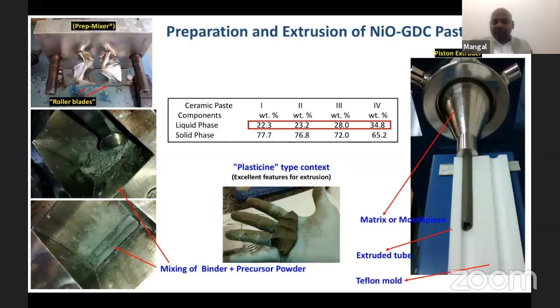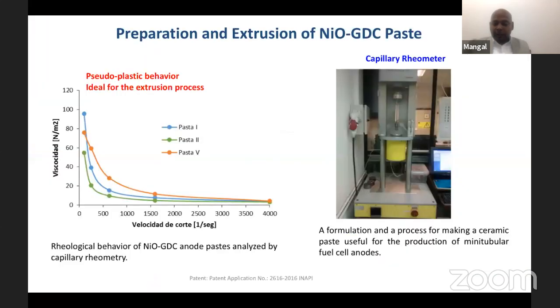So immediately we thought, okay, we can analyze the paste, to see how long it will keep its own characteristics. So we tested, and we waited nearly 3 months, and till 3 months it didn't lose them. So we filed the patent. Initially we applied for the national patent, and that was approved, and the next step, we applied for the international patent. So using this paste, we started fabricating the tubes.